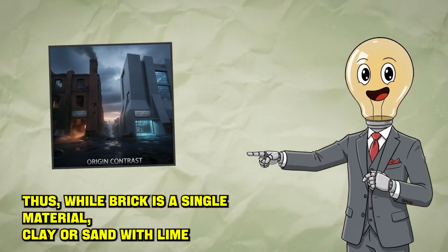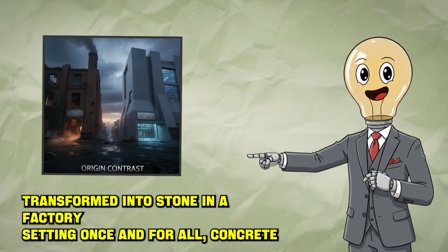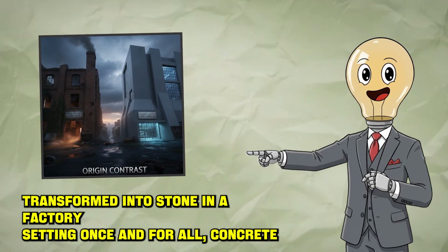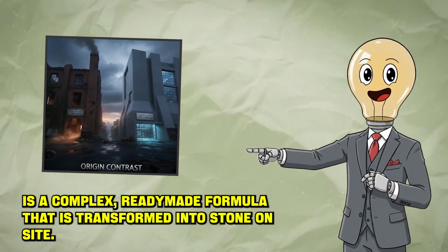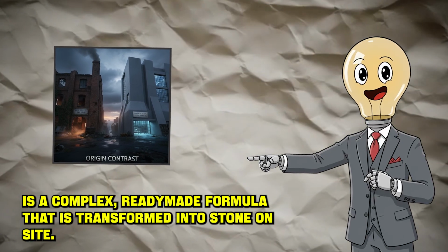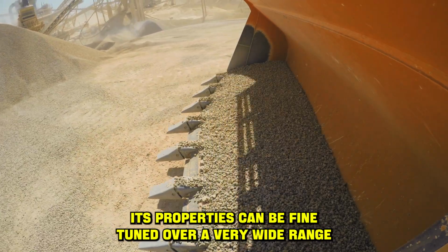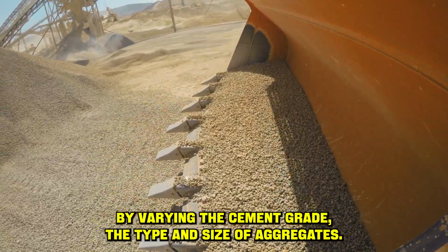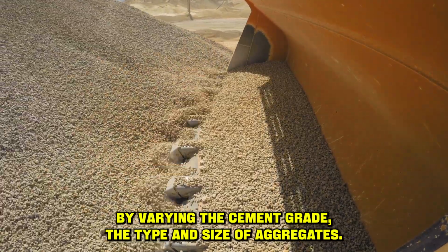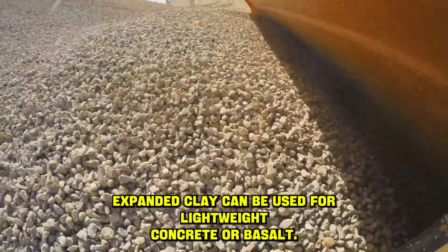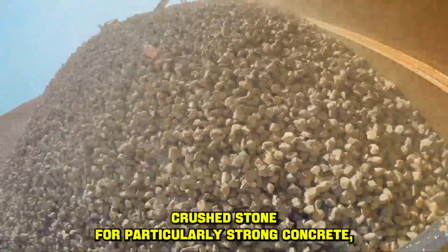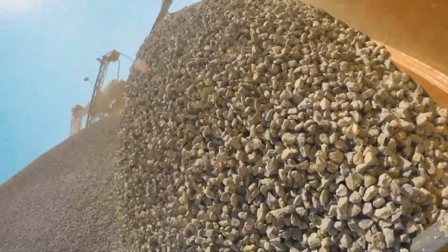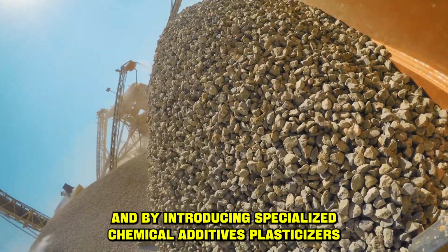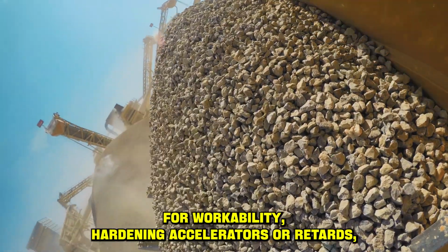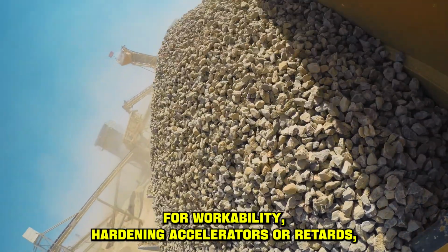Thus, while brick is a single material, clay or sand with lime, transformed into stone in a factory setting once and for all, concrete is a complex ready-made formula that is transformed into stone on site. Its properties can be fine-tuned over a very wide range by varying the cement grade, the type and size of aggregates. Expanded clay can be used for lightweight concrete or basalt crushed stone for particularly strong concrete, and by introducing specialized chemical additives, plasticizers for workability, hardening accelerators or retarders, and air entraining agents for frost resistance.